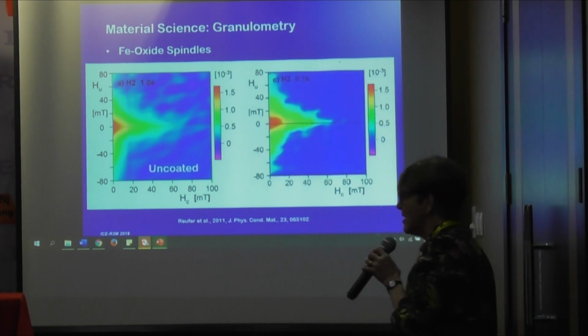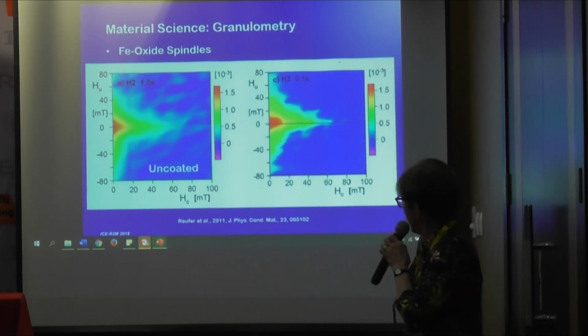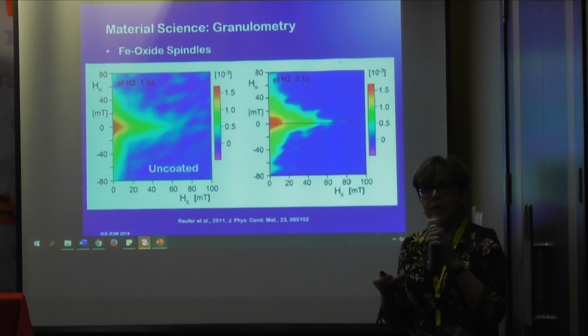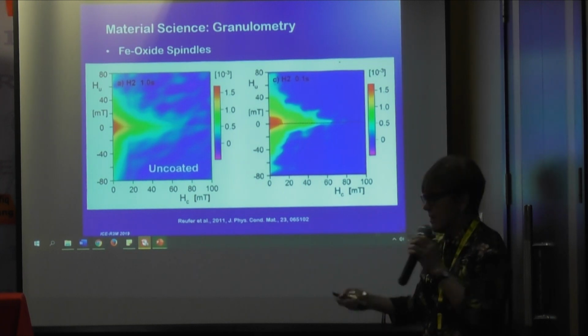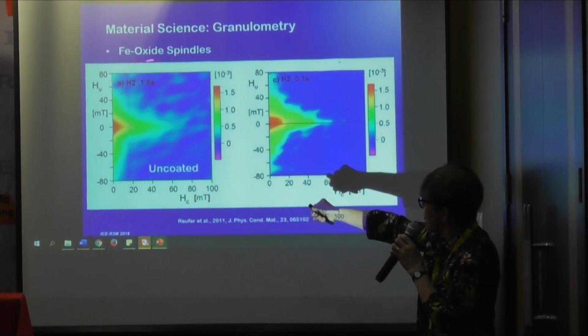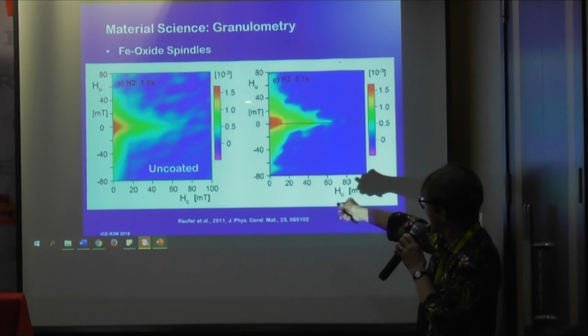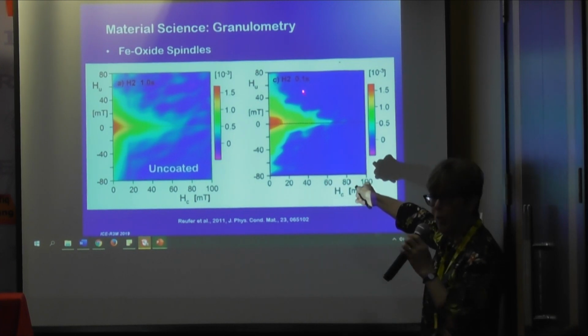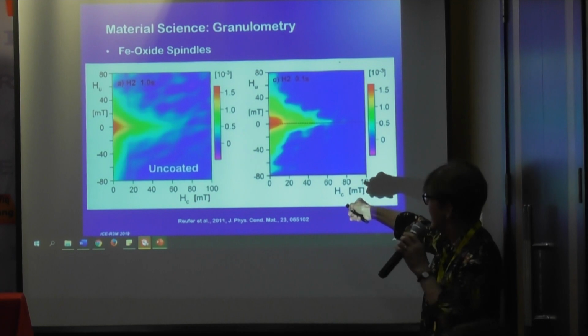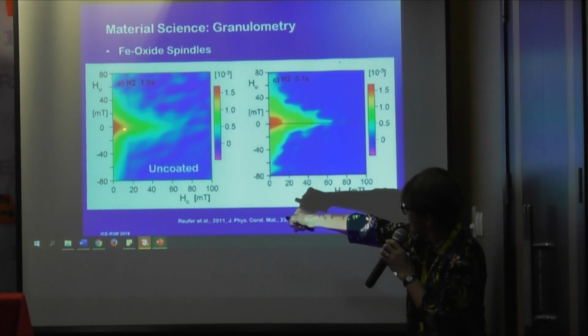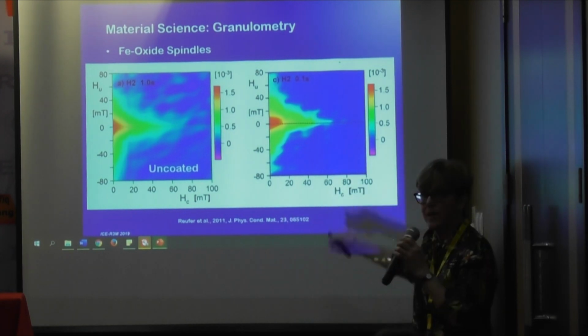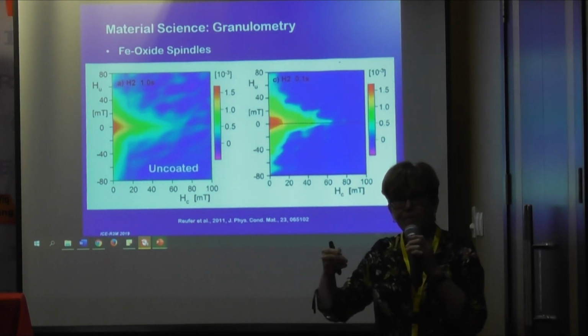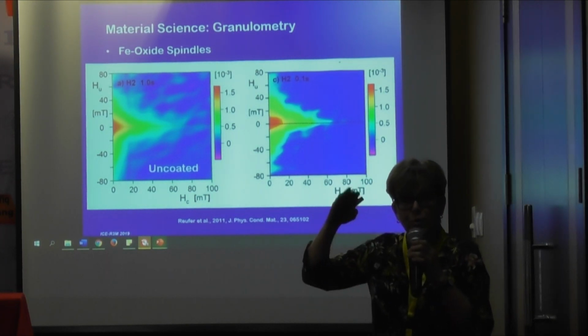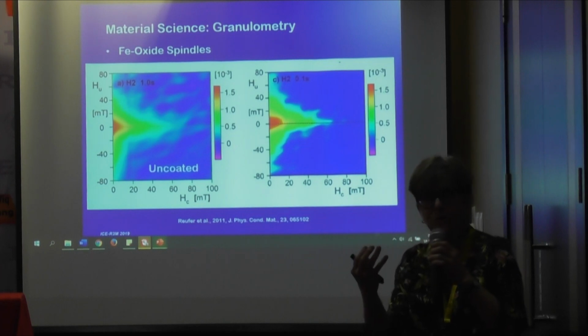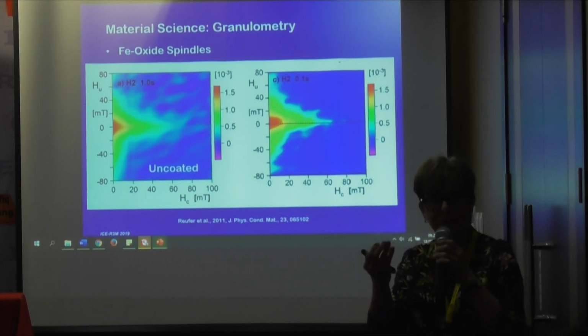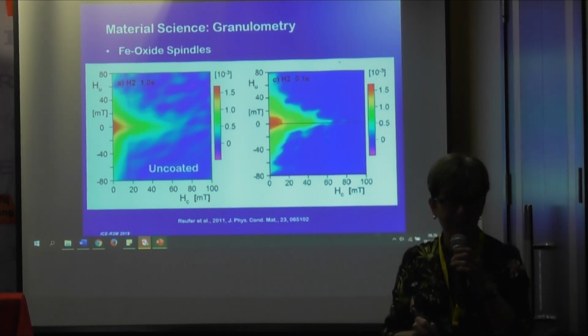And that's telling you it's very common for what you find for superparamagnetic particles. Okay, next. So we said, okay, if it's superparamagnetism, then maybe time should be playing a role. So in this case, we measured at 1 second averaging time, and then we remeasured it at 0.1 second, 100 milliseconds. And you can see what happens is the FORC distribution comes out this way. Because we're measuring faster, if our sample is relaxing, then we should see more of the signal, because part hasn't relaxed in the 100 milliseconds that has relaxed in the 1 second.